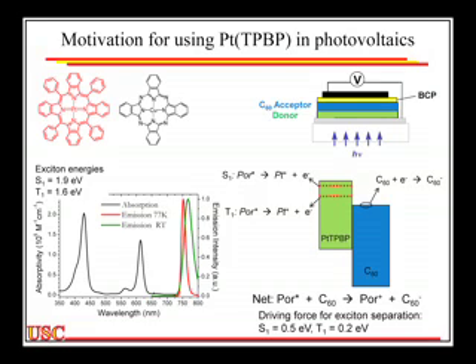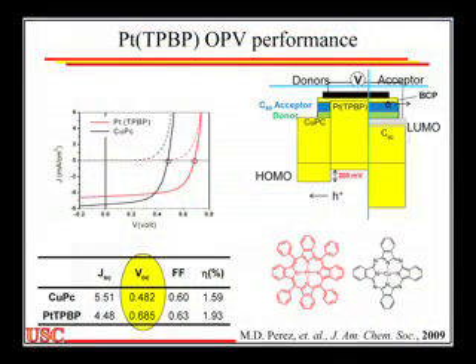And so if we look at these, we can actually estimate that. So we can estimate what the oxidation potential for the excited state is for both the singlet and the triplet. And so this is the triplet's oxidation potential and the singlet's oxidation potential. This is the reduction potential for C60, and you can see it's just fine. Both the singlet and the triplet are fully competent to charge separate. And so if it had failed this test, and I showed you the next data where we actually get a nice IV characteristic, you would have wondered about the test, but it works fine. So it explains, sure enough, we get an IV characteristic that we expect.